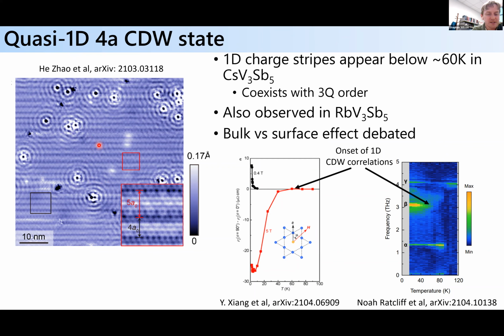Okay, so then looking at lower temperatures, initially reported in the cesium system by Ilya Zeljkovic's group, is this sort of quasi one-dimensional 4a component of the CDW order. Okay. And so this, again, as I mentioned, sits on top of this 3Q order, okay? And it turns on below a lower temperature scale, so below about 60 Kelvin. And there's no real sharp thermodynamic signatures, for instance, in susceptibility or heat capacity for this. So it'd be somewhat of a crossover, basically, if it's a bulk effect. It's also been seen in the rubidium system more recently. And I think my understanding is in the potassium system, STM sees it less frequently.